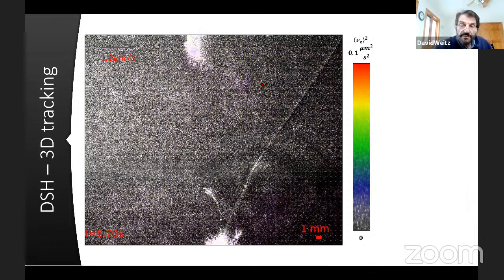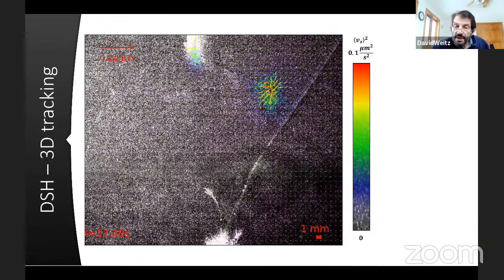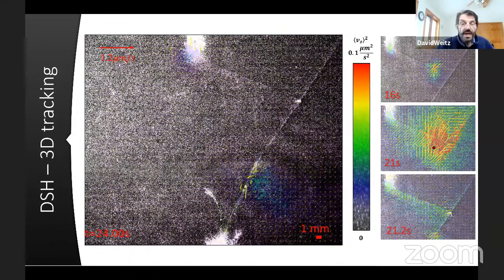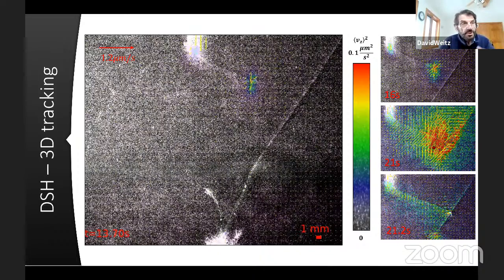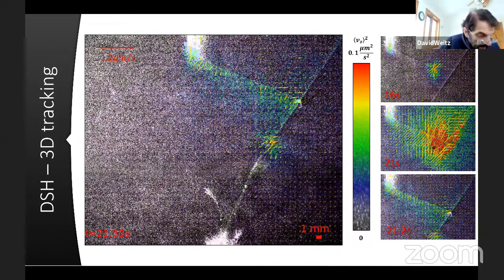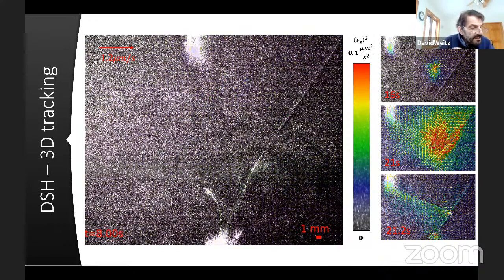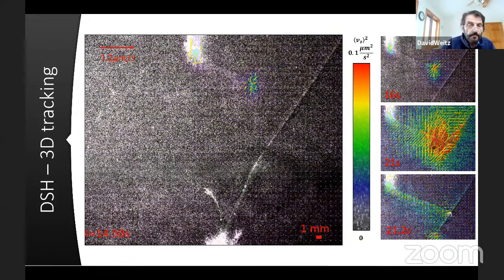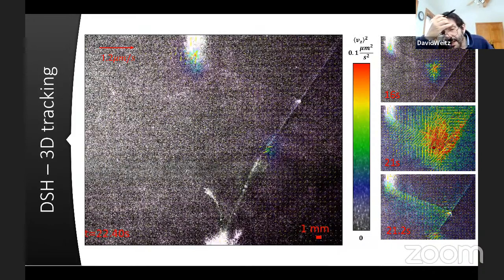And this is just looking at the velocity field around the crack in 3 dimensions. And here it's shown here. So again, now you can see the wide range over which the strain is going, but these are minute strains that you can measure because you're doing this holographic method, this interference method, looking at the speckles and how they interfere. You can measure the motion of the cracks far, far away. And so again, here's some examples of watching this.